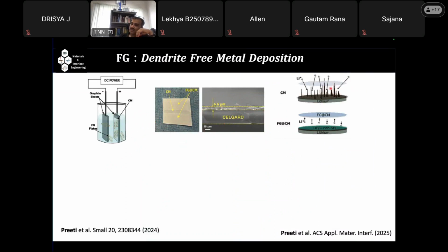And this lithium fluoride interface will help in not forming dendritic lithium deposition, even if you shuttle lithium back and forth very fast. Because if you do very fast charging and discharging, which is almost always required for a battery, then you will have a non-uniform deposition of lithium, and hence dendritic deposition, and the battery will get shorted. So this is one of the problems in the current battery industry.